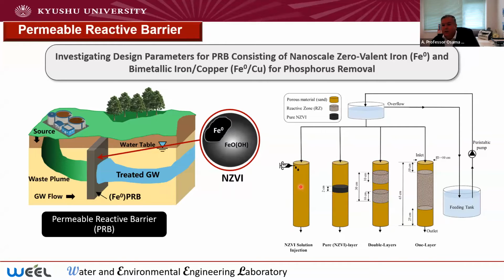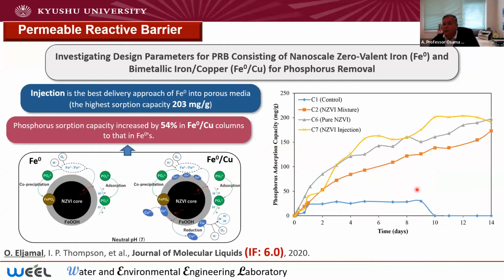We use, for example, injection. We use one layer of our nanoparticle, two-layer mixing, and actually more than 12 scenarios to find the best way to introduce the nanoparticles into the permeable reactive barrier to remove the phosphorus in this case, and maybe in other cases, we can remove different contaminants. So in this study also, we clarify the mechanism of the removal of phosphorus from the groundwater using the bare iron and the bimetal.